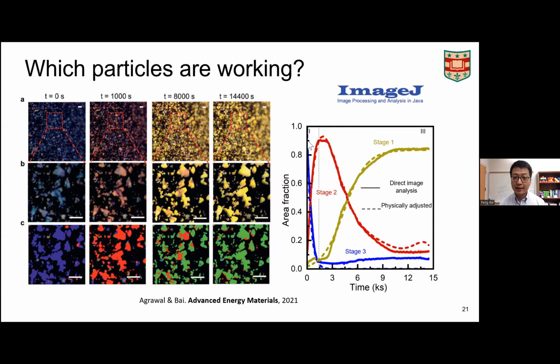to some standard RGB color for later analysis. And he identified that, shown on this diagram, initially the area fraction is 1, fully in the color blue. The blue color will go down because the red color comes up. And then when you reach the maximum areal fraction of the red color, the blue color reaches a minimum, meaning that almost all blue particles have been transformed into the red particle because more lithium ions have been accommodated into that particle. And after that, you start to see the emergence of the gold color coming up, and the red color will now go down.